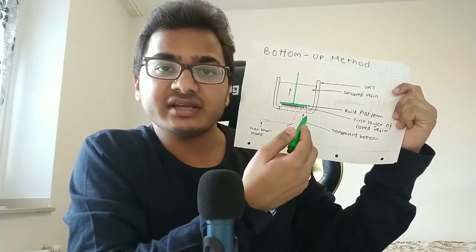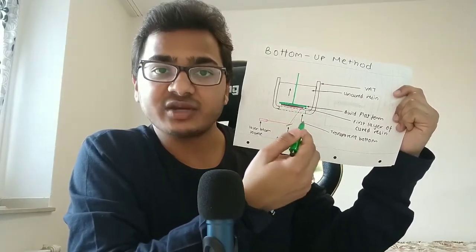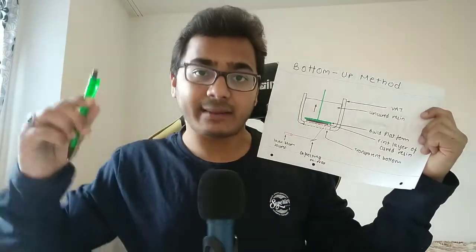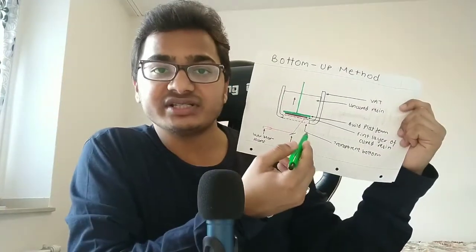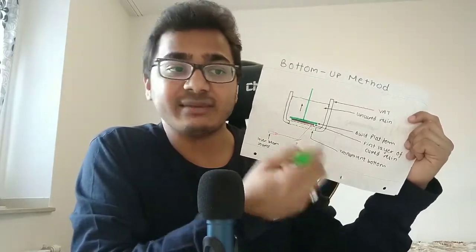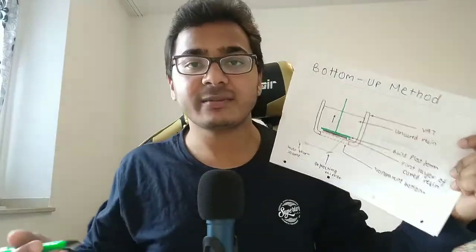As I explained, we have a silicone coating which prevents the component from sticking, but it doesn't prevent it completely. You cannot detach the component abruptly because it might damage the component surface, so you have to do it slowly, which affects productivity and makes it comparatively slower.